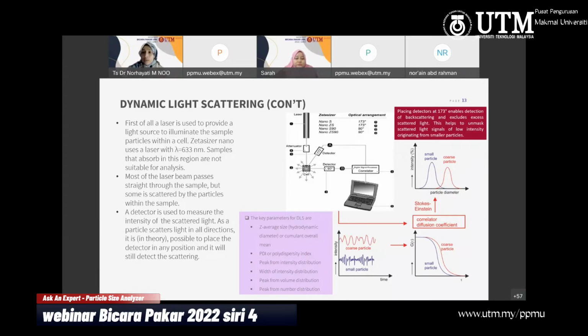So why did they come up with this? Because they found that placing the detector at this angle enables detection of backscattering and excludes excess scattered light. This helps to unmask scattered light signals of low intensity originating from smaller particle sizes. So that's why they came up with this type of detector placement for this machine. You can see here from the intensity, the small particles are in the front and the coarse particles at the back.